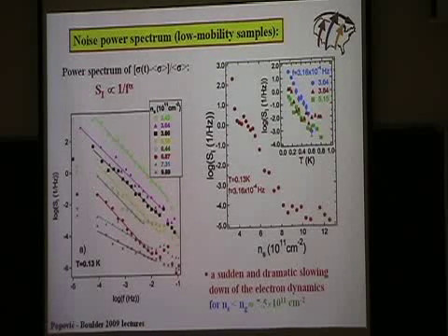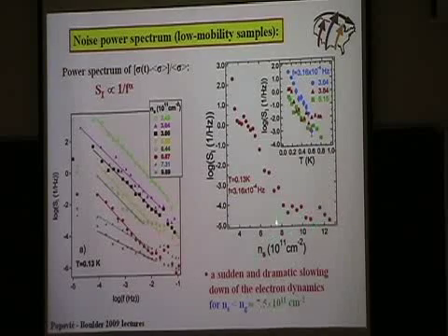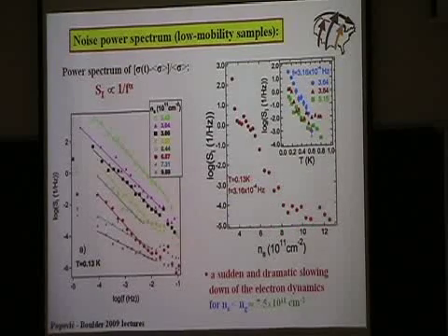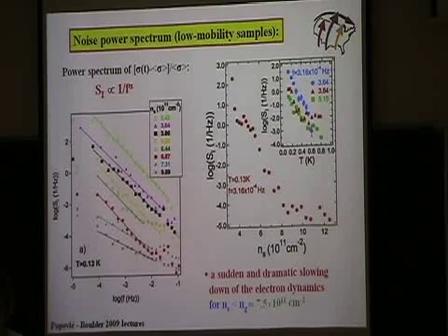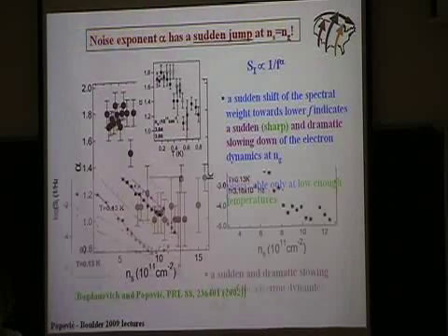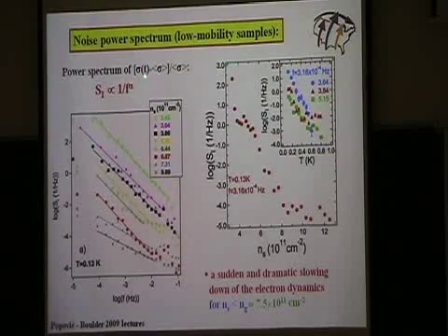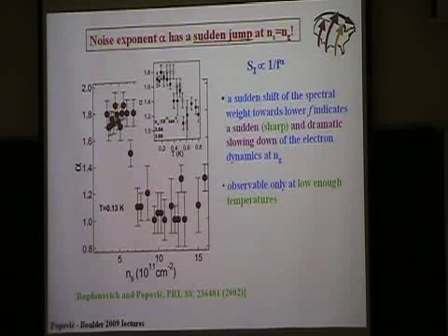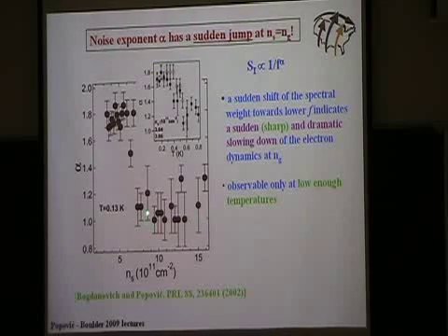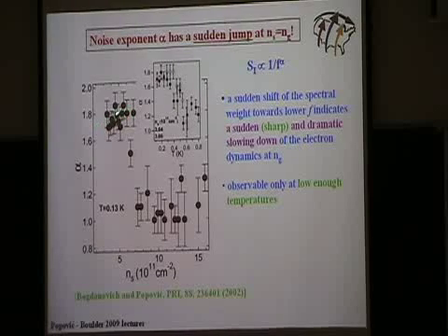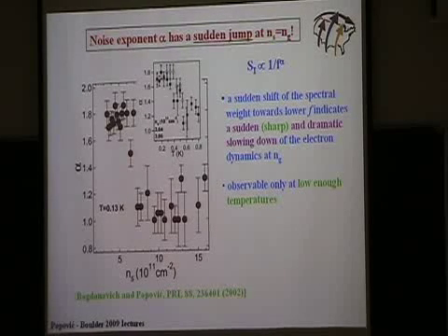Okay, so what we see from here is that the noise slows down dramatically below this density. The dynamics slows down dramatically below this density Ng. And the most spectacular, I think, is the behavior of this exponent alpha as a function of density, which is shown here. So you see for high densities, this exponent is 1, so it's a pure 1 over F noise, if you like. And then at Ng, the noise jumps up to a very high value, about 1.8, which suggests that we have a very small number of states that contribute to the transport.